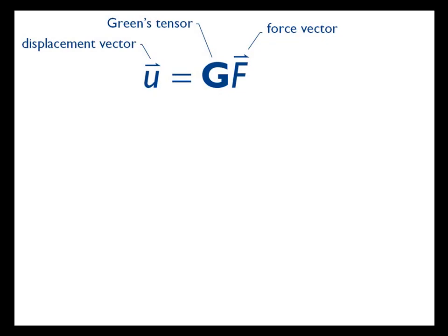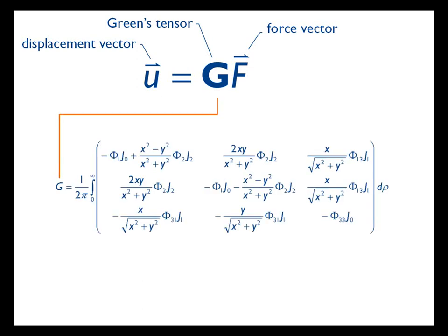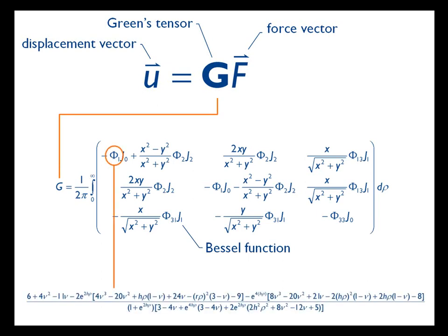We use the Green's tensor, a 3x3 matrix that couples an applied force to the resulting displacement. In the case of surface deformation of a finite thickness film, the Green's tensor incorporates several Bessel functions and unique, intricate characteristic terms that are definitely best manipulated with a computer. Because we're interested in the response not from a single force but from a shear stress, we integrate the Green's tensor over the circular adhesion site area.